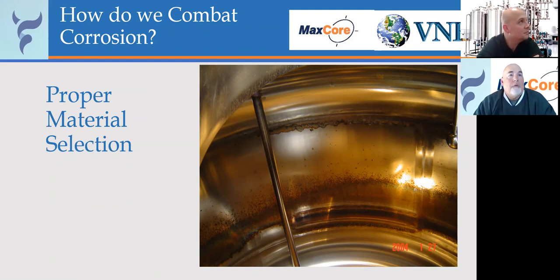Where they had an issue with the tank, and it had completely turned bright red and all the piping had eaten out. In this particular case, it was a chloride solution used to spray on peanuts, honey roasted peanuts, that had a high chloride content. They didn't want to take the jump to do the proper material up front. They had to go back in, get the tank fixed, move it somewhere else in the system, and replace all the piping in higher alloy from that location on. So again, a lot of times it makes a lot more sense to spend the money up front and do the correct materials rather than try to fix it later on down the line.